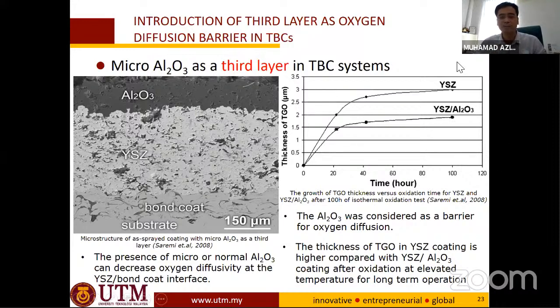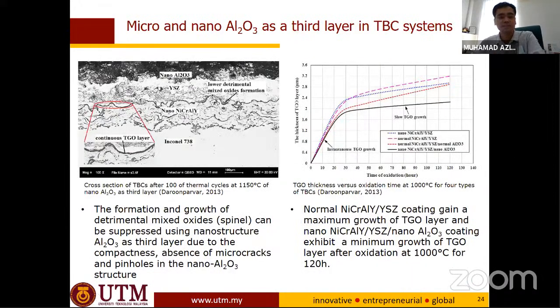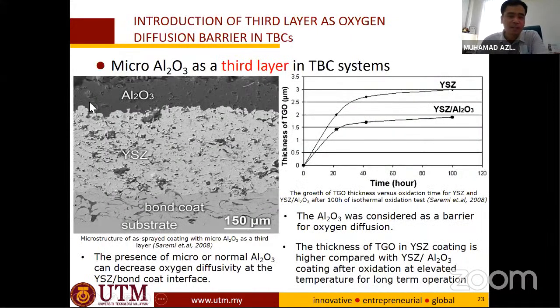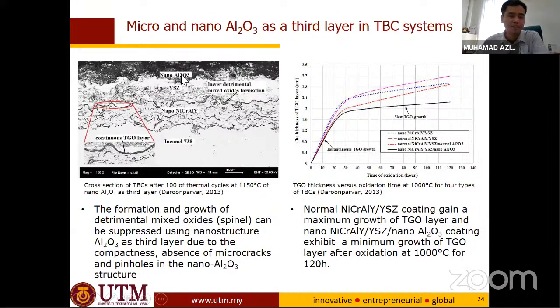So that means based on our research, we found that that's good, but we actually go to a further extent. What we actually do, for example in this slide, this is the normal alumina, so we call it micron size alumina. And then we use a nano alumina powder. What we obtain, you can see here, this last line is where we use the nano alumina. So meaning that if you have the nanostructure here, you can further reduce the TGO thickness. That's based on our findings.